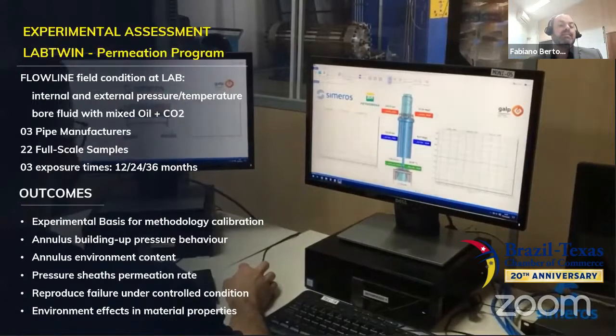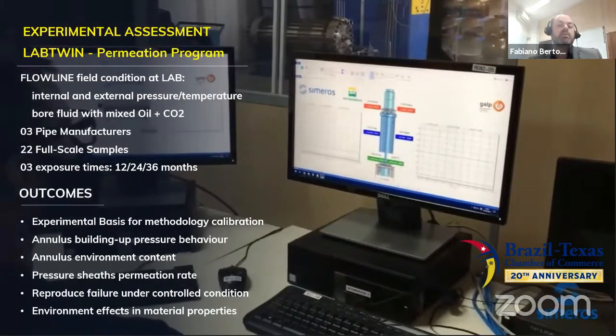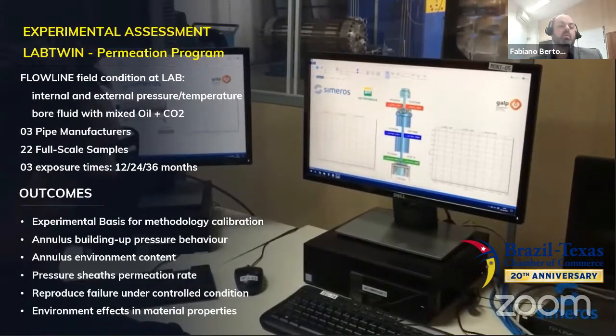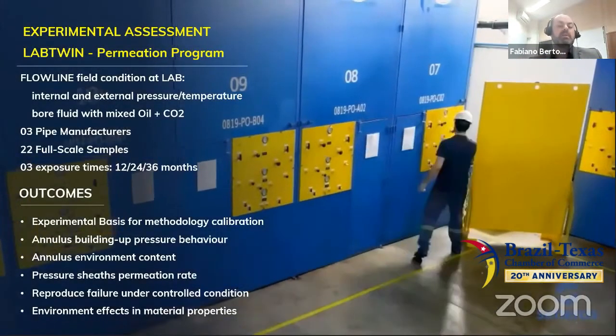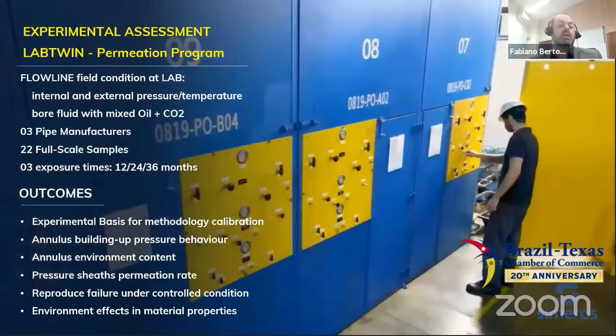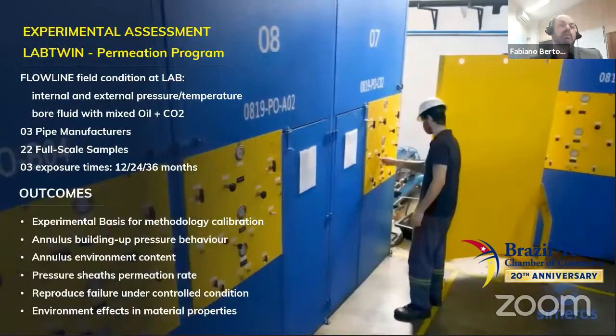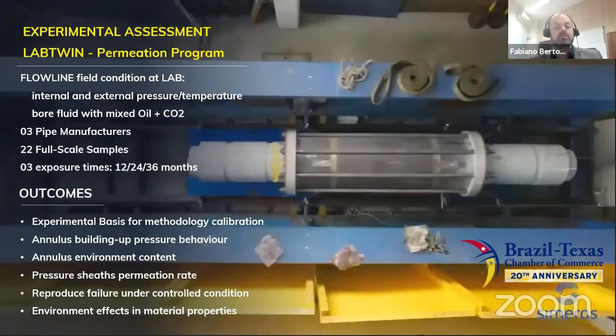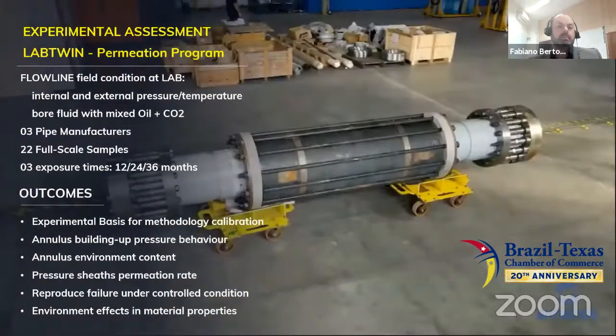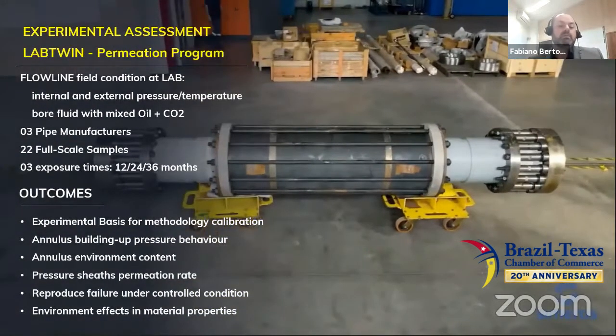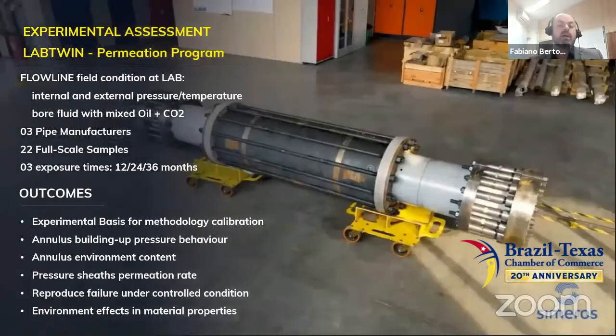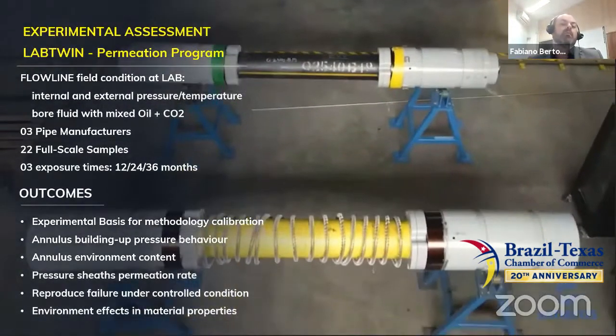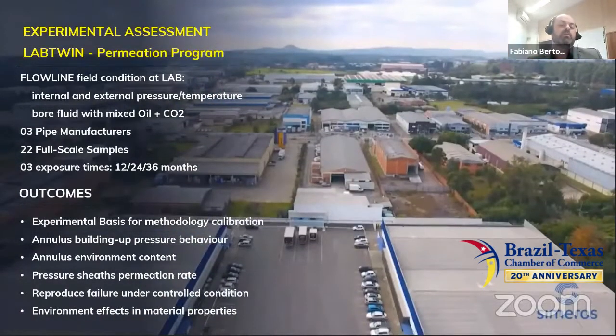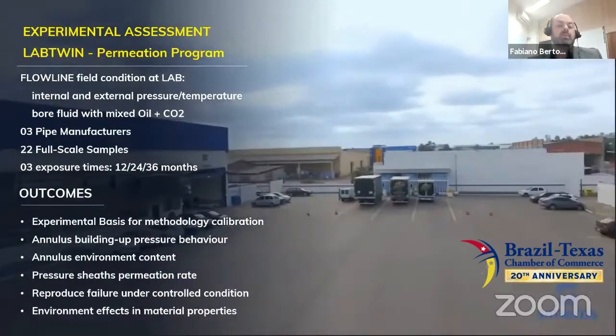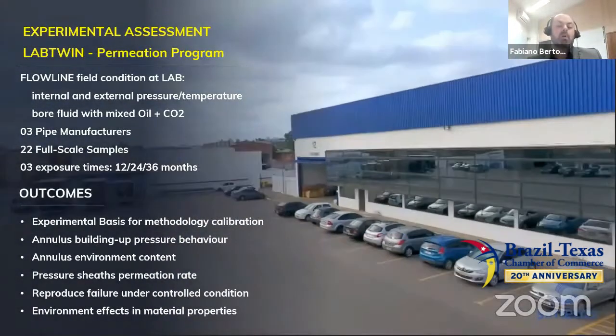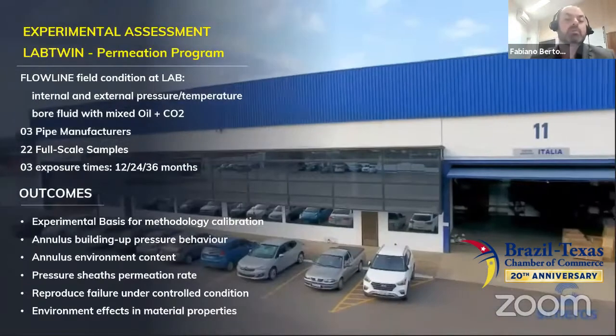And besides that, the testing matrix considers a combination of 3 different pipe manufacturers with 2 different pipe structures representing production and gas injection application, and also 3 different aging times, 12, 24, and 36 months. The proposed setup will result in a permeation process that will deliver a characteristic field annulus environment for each sample under laboratory monitoring. The project includes protocols for laboratory instrumentation, monitoring, and dissection procedures in order to obtain the maximum